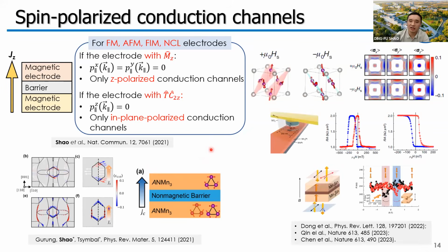For example, in some non-collinear antiferromagnetic metals, the anisotropic spin texture on the Fermi surface will contribute to the non-collinear spin polarization of the conduction channels. So using such a non-collinear antiferromagnet as an electrode to build a tunnel junction, we can get a TMR by matching these conduction channels. This mechanism of matching conduction channels has recently been confirmed by two experiments.